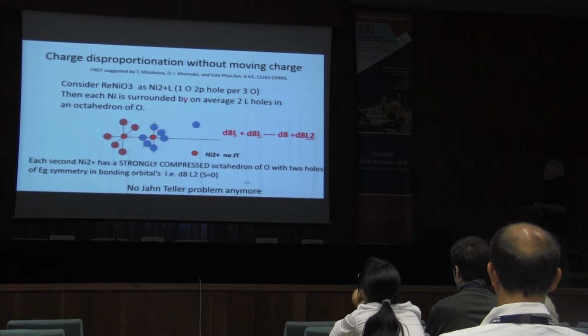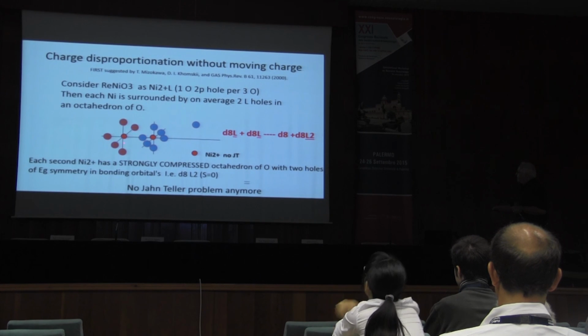Then each nickel is surrounded by an average of 2 oxygen holes in an octahedron, because each nickel has an octahedron of oxygen. And if I have 1 oxygen hole per nickel, that means I have 1 hole per 3 oxygens. That means I have 2 holes per 6 oxygens. And I'm going to put them into a bipolaron. Okay? And what they will want to do is, if you can't have 2 holes on this octahedron and also on that octahedron, bonding strongly with a sigma bond to the center.